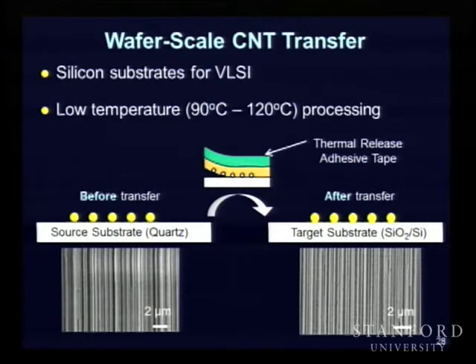Look, this transfer can be done at a very low temperature, 90 to 120 degrees C. Now think about that: if you can transfer from one substrate to another substrate, nobody has said that you can do it only one time. You can keep transferring multiple times from multiple source substrates to the same destination substrate, and your carbon nanotube density should go up. That could be a way to increase carbon nanotube density.